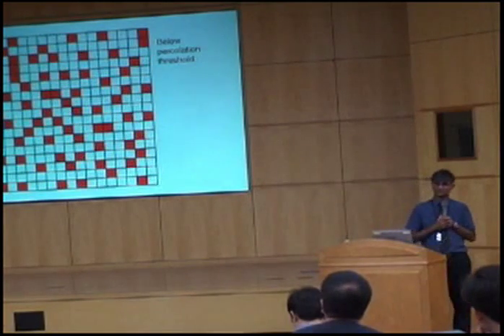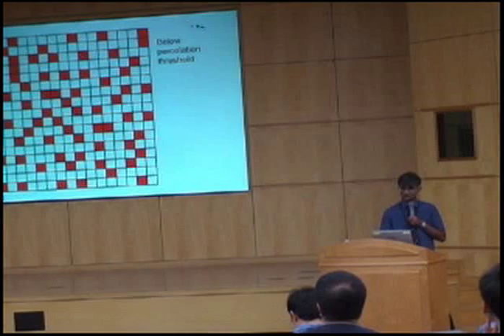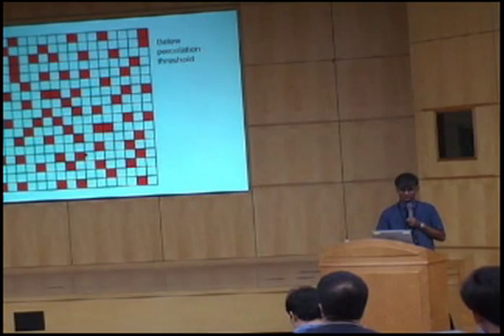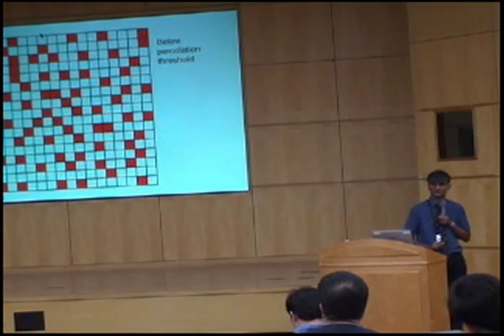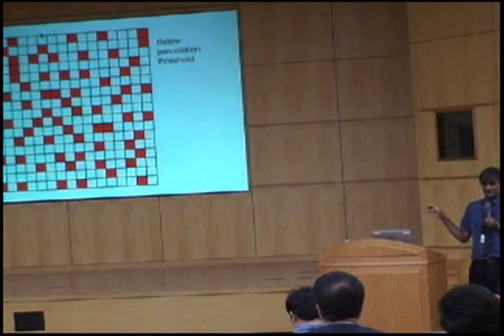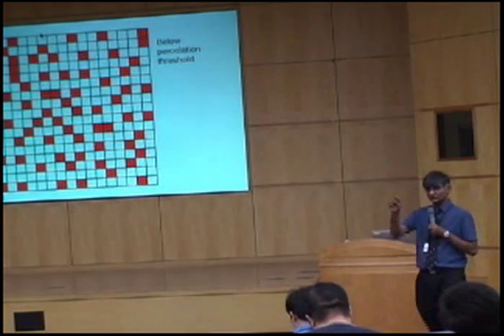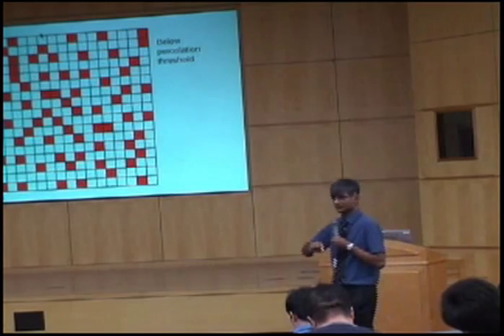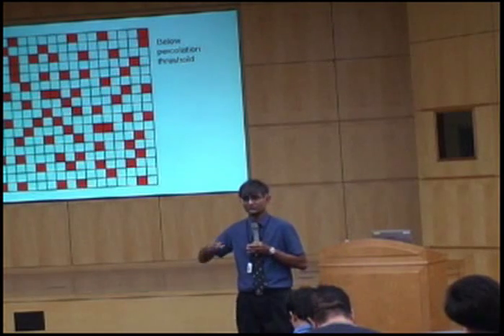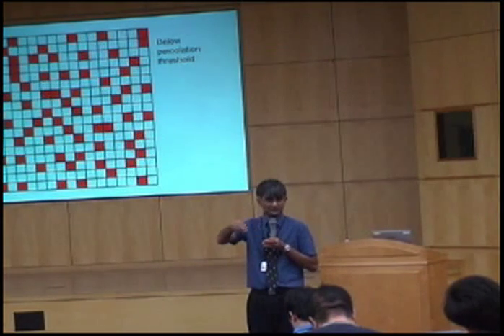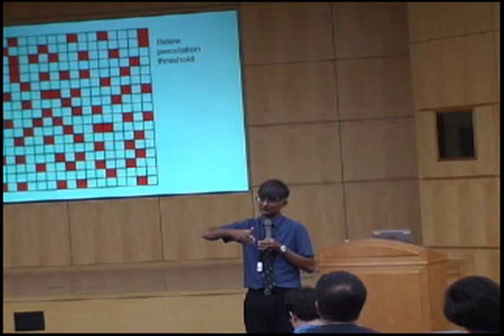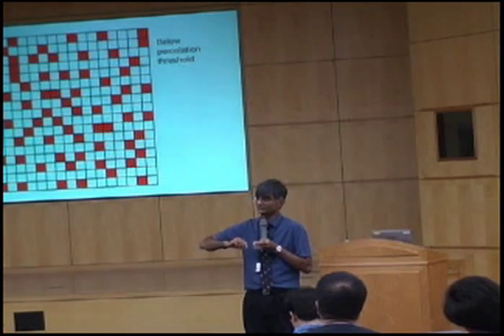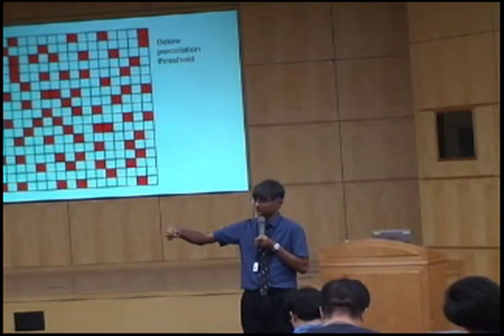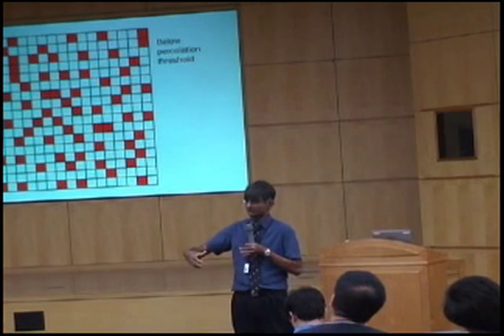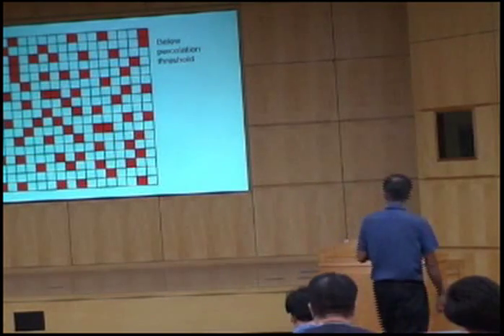This microstructure, on the other hand, is below the percolation threshold, and I cannot draw a continuous line through the austenite. Okay? And what I claim is that once we go below the percolation threshold, the sample breaks, because we've got these regions of martensite which are formed. Okay? In what used to be austenite. And we can no longer get the ductility from the austenite, and the sample then breaks.